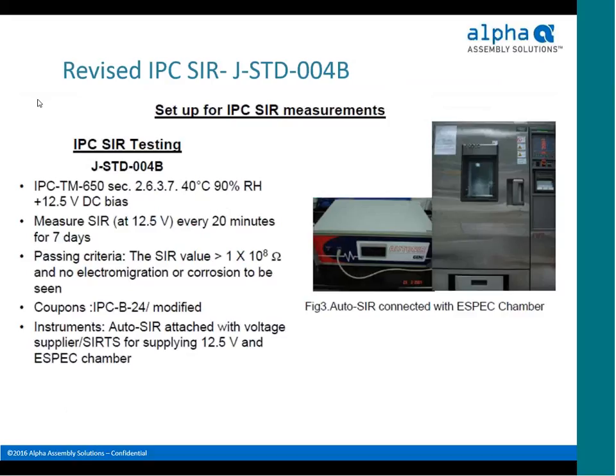So this test condition is a little bit different. It's based on the old J standard 004A. However, they've changed the temperature to be 40 degrees C. The humidity is now 90% RH, and the bias level is 12.5 volts per spec. In this test, the SIR resistance is now measured every 20 minutes for 7 consecutive days, which is a big difference between the old check it 3 times over a week methods.